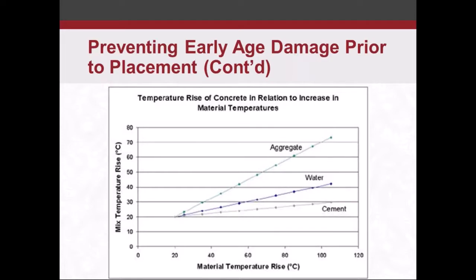This table here is from the Portland Cement Association, and we can see the slope of this line. I didn't calculate it, but it's probably about a 2 to 1. To the left, we've got mixed temperature rise. Here on the x-axis, we've got material temperature rise. So as we raise the material temperature of, say, the aggregates, we're going to raise the overall mixed temperature. And remember, the aggregates are about 2/3 by volume of our concrete. So you get a lot of bang for your buck by raising the aggregate temperature. About a 2 degree temperature rise will give you about a 1 degree overall mixed temperature rise.